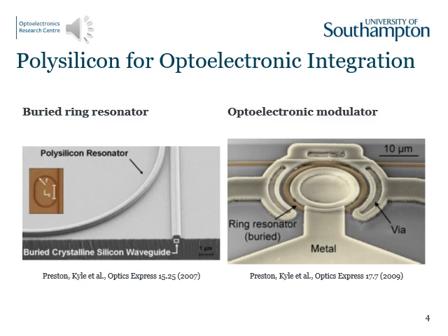To avoid this, the laser annealing process from thin-film transistor electronics was adopted, in which a thin film of amorphous silicon is deposited at low temperatures and crystallized by excimer laser exposure. Here, the short exposure times prevent excess heat transfer to the substrate. Using this method, a GHz electro-optic modulator was demonstrated in CMOS-compatible polysilicon.